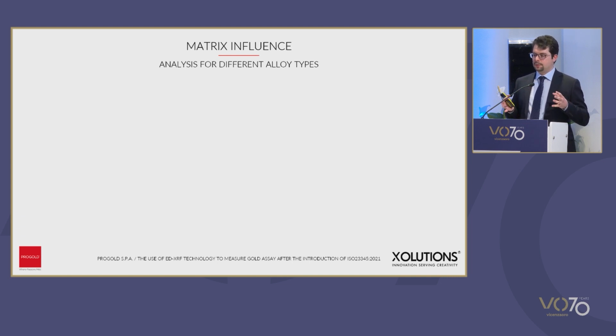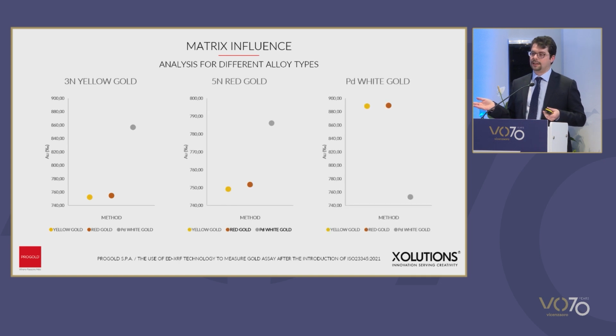What happens, for example, if instead of using a calibrated method for a specific composition, I want to measure the fineness of gold of another alloy? I'll make an example. And we crossed some data. We took the red gold, and we used the same method that we had used for the yellow gold, in order to measure the importance and the influence of matrix. And we see it here.